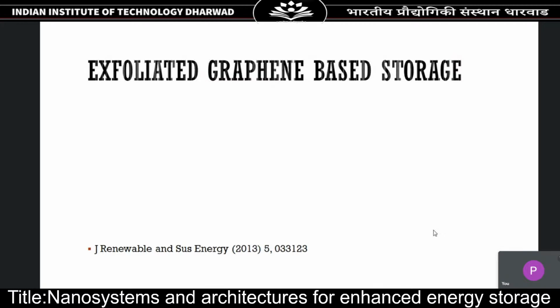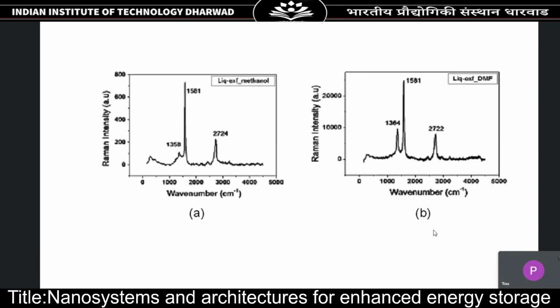So let us go to the next system, which is exfoliated graphene-based storage, which was published in Renewable and Sustainable Energy. What we have done is we have taken graphite and chemically exfoliated it. Not only chemically, it is a combination of chemical exfoliation and mechanical exfoliation. We have done ball milling, and we have also used a chemical exfoliating agent, which is 1-pyrene carboxylic acid. And we have done the liquid exfoliation in methanol and DMF.